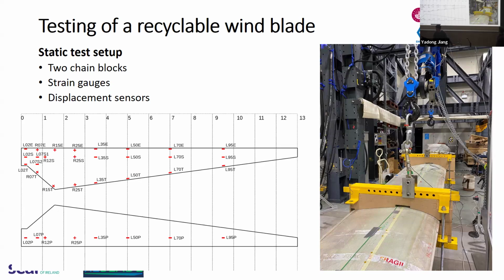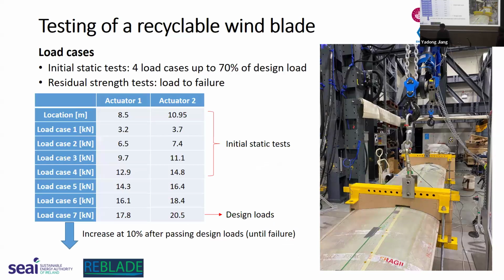And besides the strain gauges, we also use fiber optic strain gauges to measure the development of strain along the blade. Okay, so in the static test, we planned for 7 load cases, and in the initial static test, we will just perform the first 4 load cases and load the blade up to 70% of its design load, because we don't want to break it, as we need to complete the fatigue test. Then after the fatigue test, we'll repeat the static test and load it up to design load. And if it survives the design load, then we increase by 10% of the design load until failure happens.